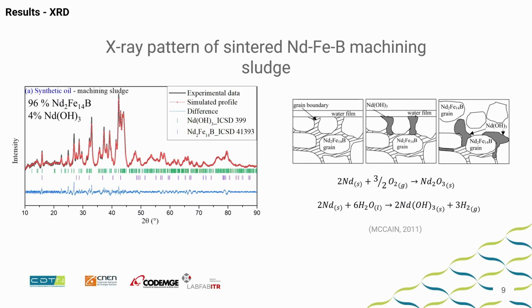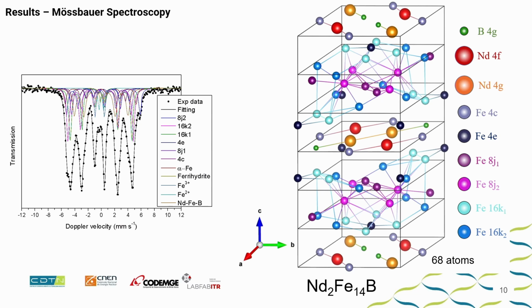And we also find hydroxide neodymium, and with this oil, this synthetic fluid, and this is always in these grain boundaries that have more probable reactions and kinds of oxidation states. This hydroxide neodymium arises with more problems arising in the grain boundary. And the study with Mössbauer spectra.